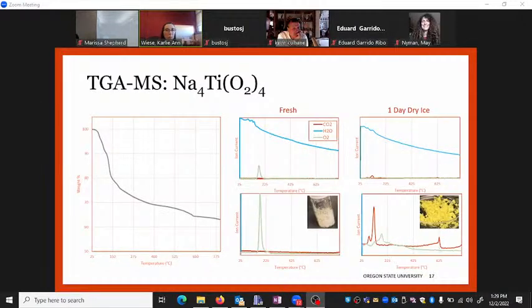So the data from that looks something like this. The first graph here is the TGA curve, so that's showing the weight loss. We started with our fresh sample, and then at the end, there was loss of CO2, water, and oxygen. The first two graphs, top and bottom, are the same result from the fresh sample. The bottom one's just zoomed in on the region down here below the water. We can see that there are no peaks of CO2 at all, which tells us that the fresh sample did not have CO2 in the structure.